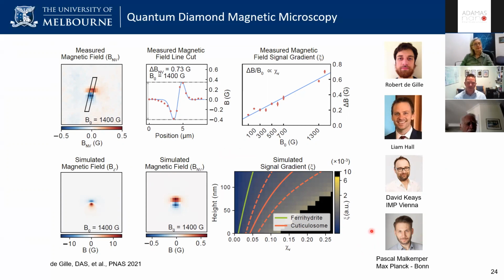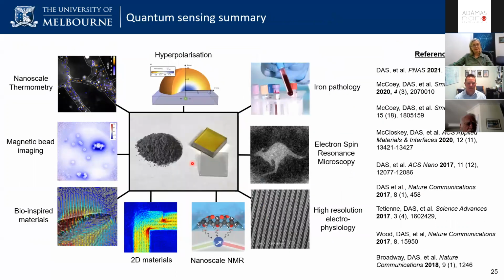And so that was a really significant study that shows the power of this diamond magnetic microscopy technique for starting to look at biological systems in situ. And the really important part about this work is that it really limits the false positives. Because you can cut out the biological sample and put it directly on, you can image where that magnetic signal is within the anatomical location of the cell. So these features are a really important property of diamond magnetic microscopy going forward.